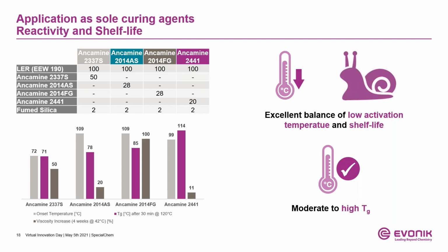A good compromise between these two are Ancamine 2014AS and the 2014FG grade, but the differences in shelf life must be considered, which is much lower for the FG grade due to the smaller particle size. Overall, the shelf life of all products is quite excellent, with a minimum of 4 weeks at elevated temperatures, and also expected to be even longer at room temperature, which is great performance for such products.